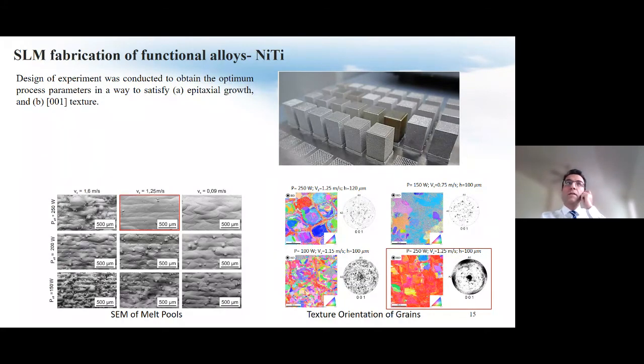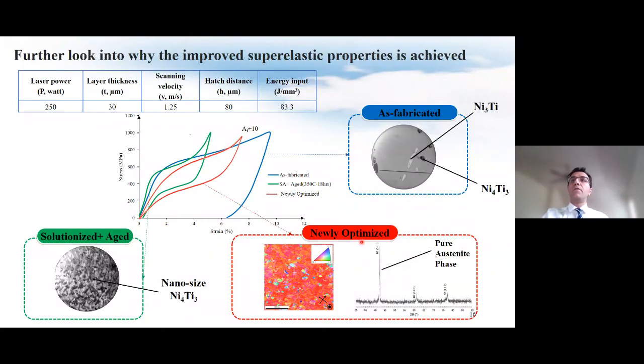Okay, to testing and doing the mechanical performance analysis. So, in this slide, I would like to show the level of superelasticity of this newly optimized specimen versus that for the state of the art in the literature. As you can see here, the red line demonstrates the stress-strain curve of our newly optimized specimen during loading and unloading of the part. Interestingly, for the first time, 6.5% superelasticity was achieved in this specimen without any kind of post-processing heat treatment.